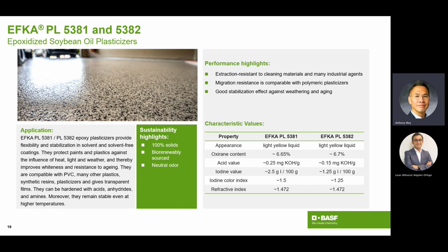The EFKA PL 5382 is a more purified version relative to 5381. So for cases where you need that extra purity, we have a solution for that as well. Being that they also have epoxy functionality, in particular with epoxy coatings, they can cross-link into the epoxy resin. So they will not migrate out of the coating once the epoxy coating is cured. Yet they will impart that additional flexibility that's required to avoid things like embrittlement in the coating.